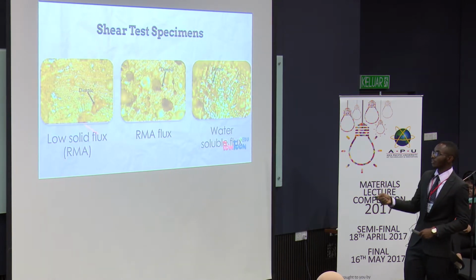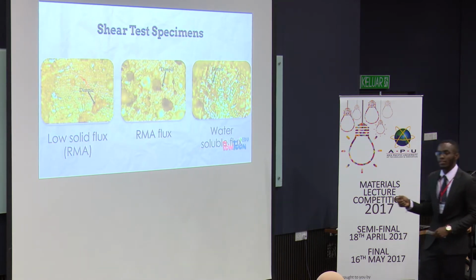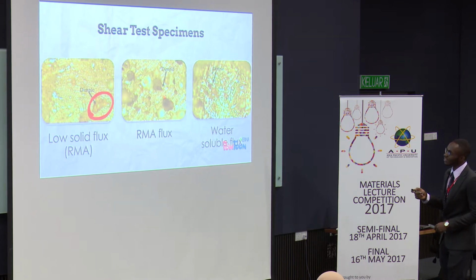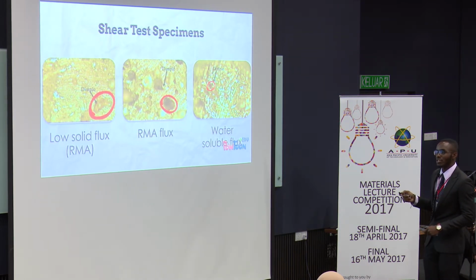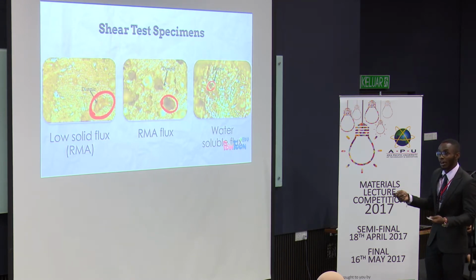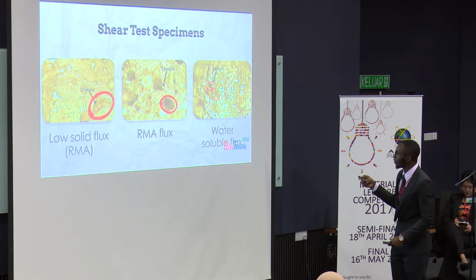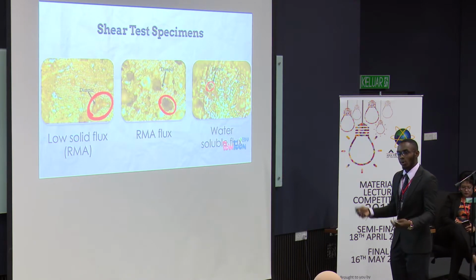For the shear test specimen, we see a huge dimple on its surface. And then we see a slightly smaller dimple, as I mentioned earlier, on the surface using the RMA flux. And the water-soluble flux has the smallest dimple.